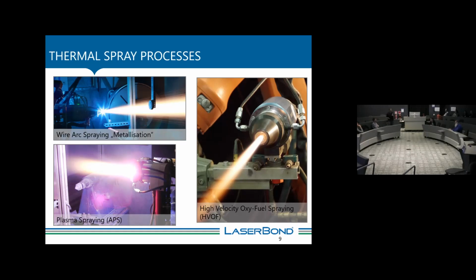And also use the electric energy to dissociate the gases, basically. After the dissociation and ionization, the gas in the electric arc recombines and releases heat, theoretically in the range of 10 to 15,000 Kelvin. So this also makes it suitable for